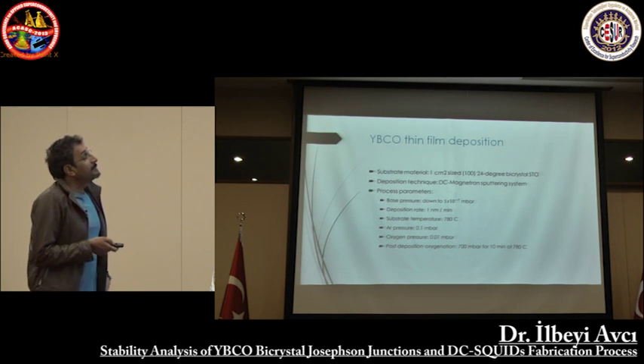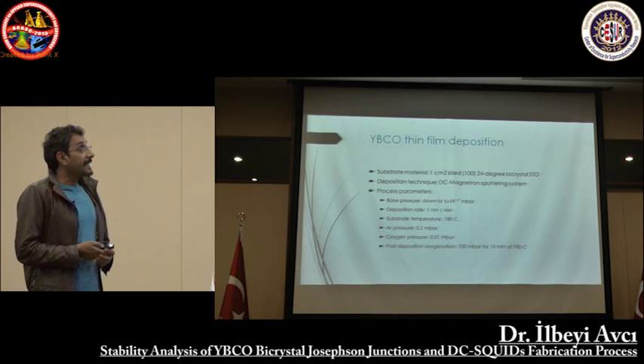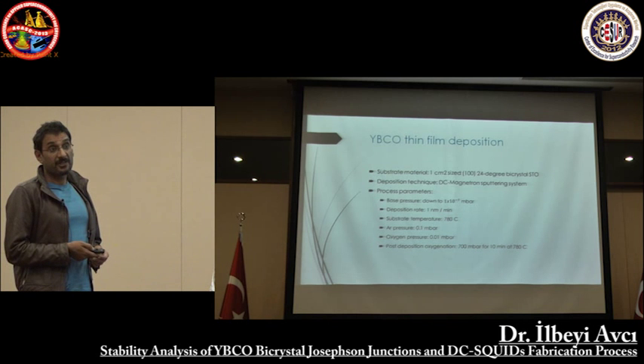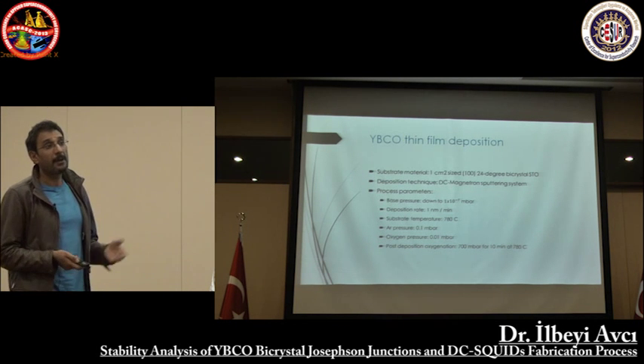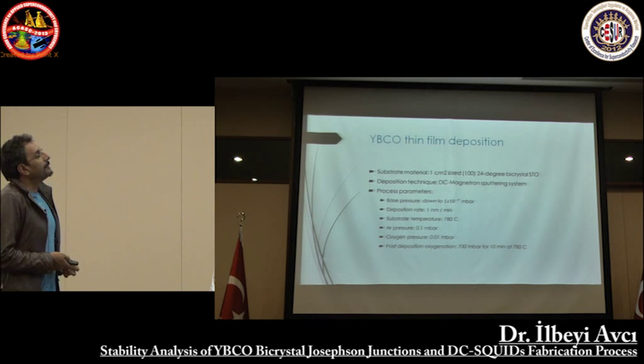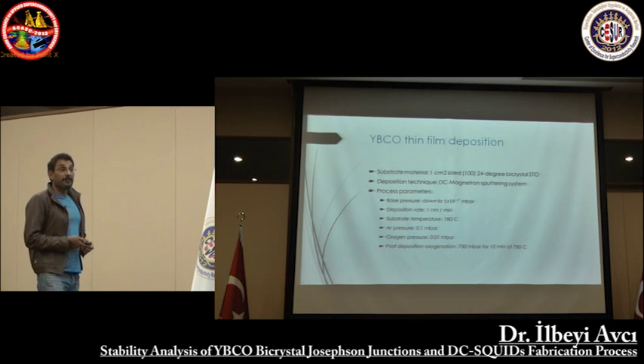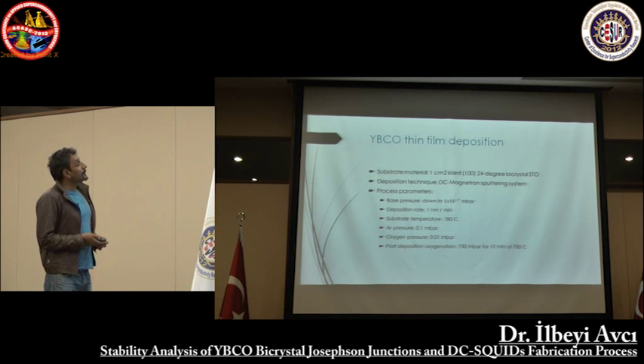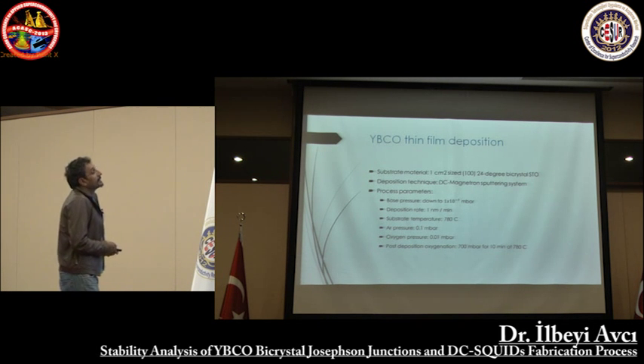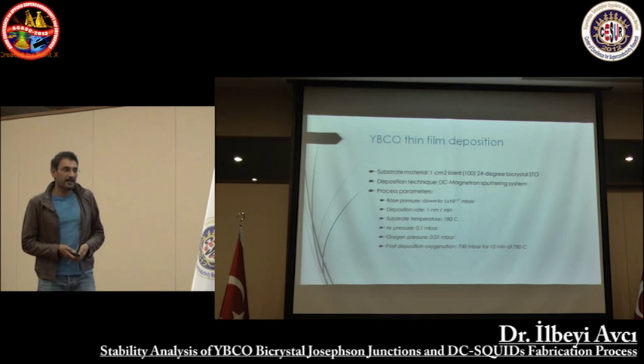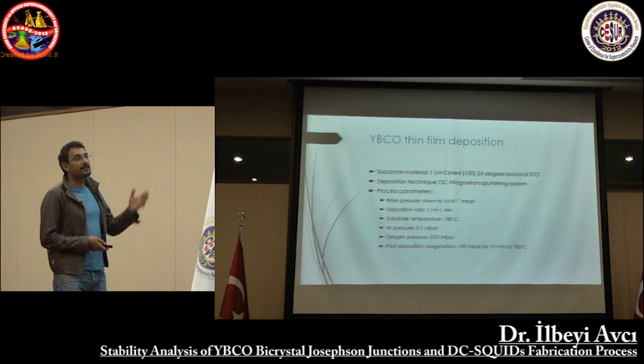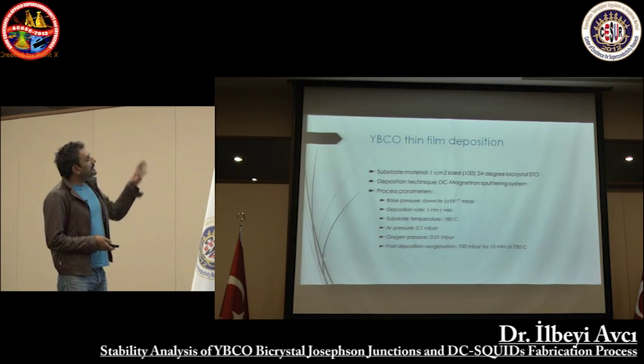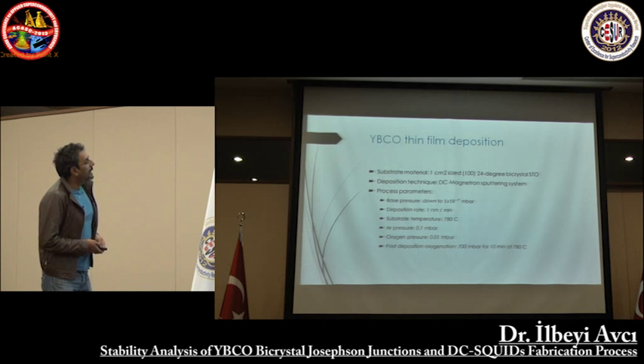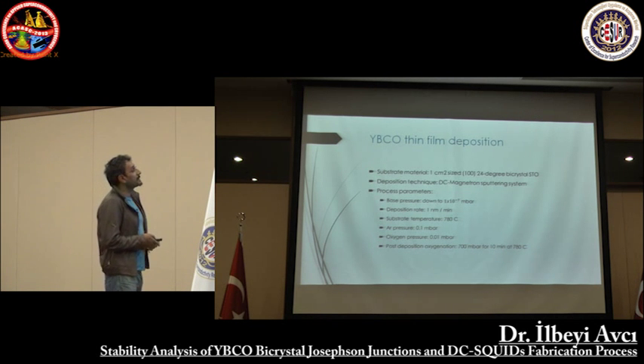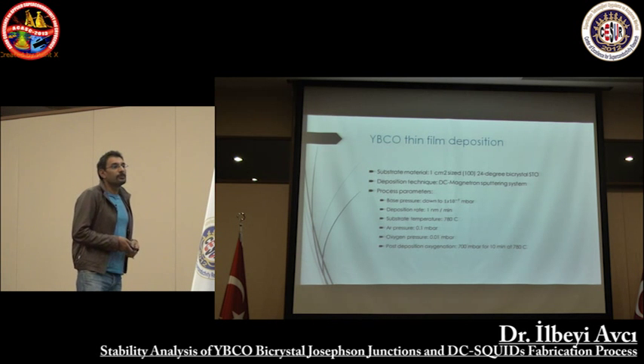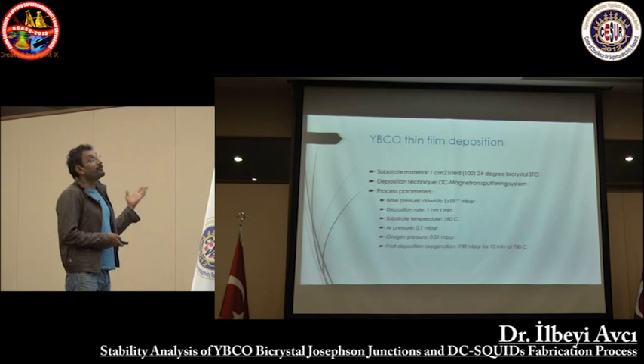The most important thing, I think, is the thin film structure for the Josephson junctions. If we are talking about high-Tc devices, it's very important to improve the thin film quality. So we have tried a lot of different parameters in our lab using the magnetron sputtering system, and we got these process parameters. We are using a base pressure down to 10 to the minus 7 millibar